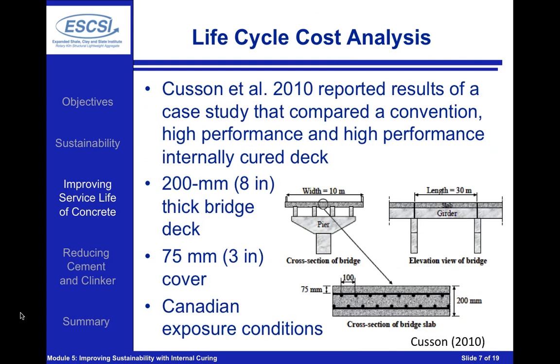Now, a life cycle model was developed by Cusson where he incorporated the effects of both the improved diffusion coefficients of our concrete with internal curing, and he accounted for the improvements by reducing the potential for cracking. So Cusson's study really examined a conventional concrete, a high-performance concrete, and a high-performance internally cured concrete with an 8-inch thick bridge deck with 3 inches of cover that was exposed to a Canadian environment.